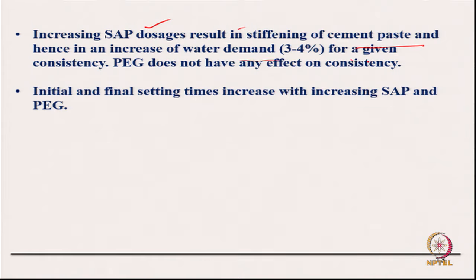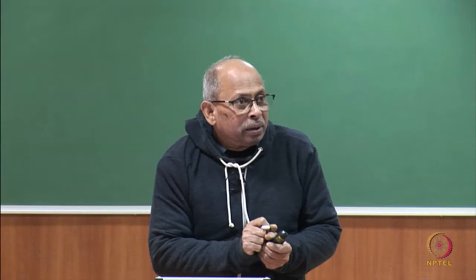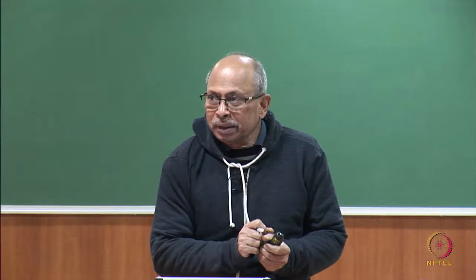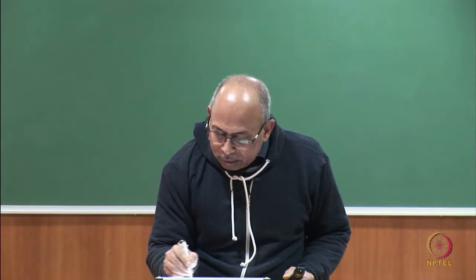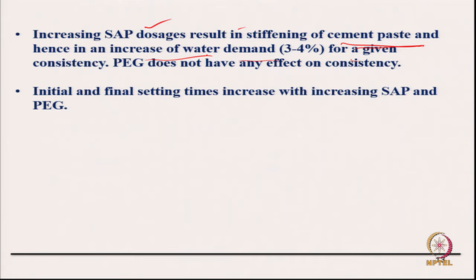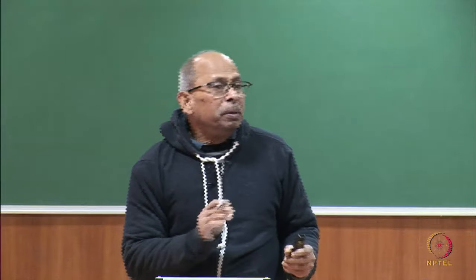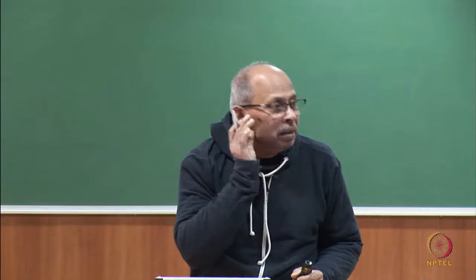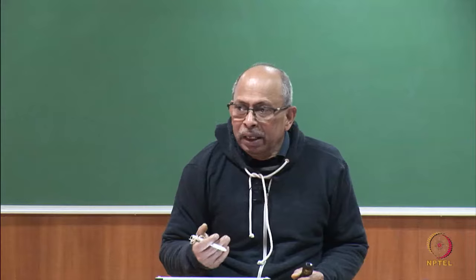Sometimes some of those SAP, that is super absorbing polymer, absorbs too much water. So, that will disturb the setting process and stiffen it quickly. So, cement paste and hence initial water demand might increase for a given consistency. Polyethylene glycol does not have any effect on this one. Initial and final setting time increase with increasing SAP and PEG. So, initial setting time increases a little bit, which means that the solidification process is delayed a little bit.